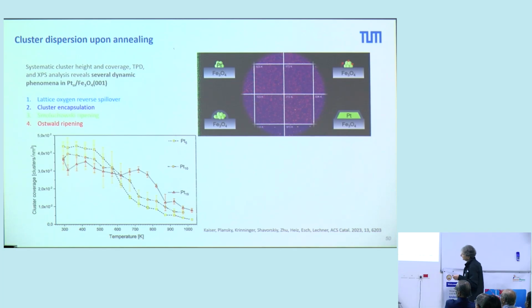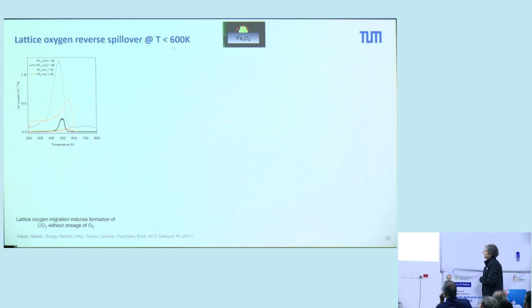Here you see, as a function of temperature, the cluster coverage for these 3 sizes. You see that the cluster coverage of platinum 5 is stable up to about 400, 450 K. And then you see a decrease of the cluster density. That means something happens. On the platinum 10, you see that they are stable a little bit to higher temperatures, and then we also have this decrease in coverage. That means there is a ripening going on. And for the largest clusters, here showing in red, it is stable up to rather high temperatures, 700, 750 K, and then you see the decrease in the coverage.